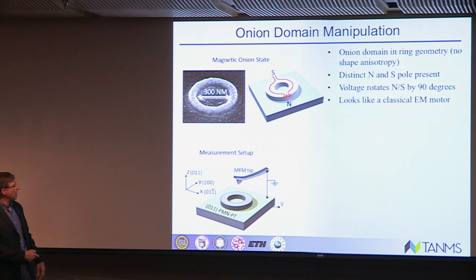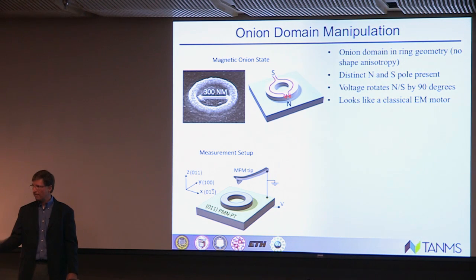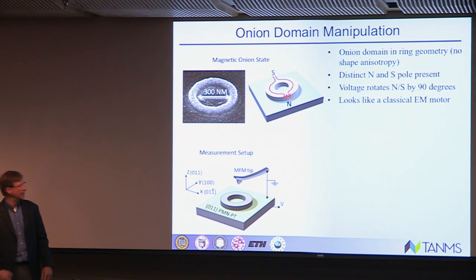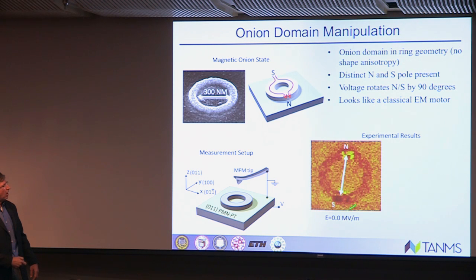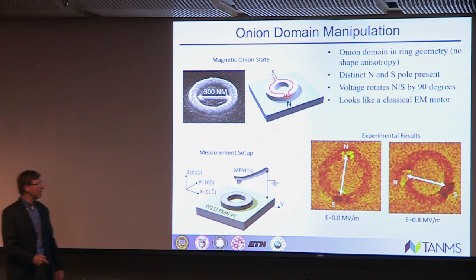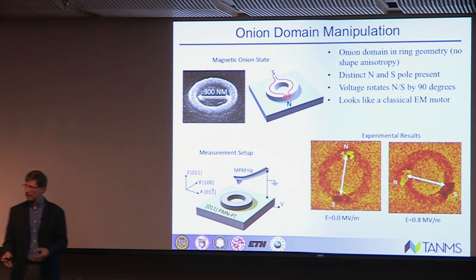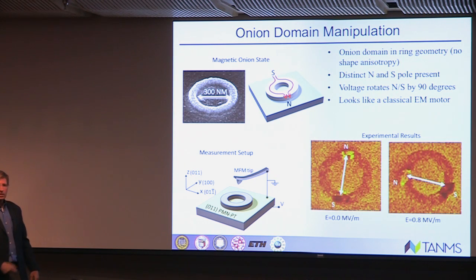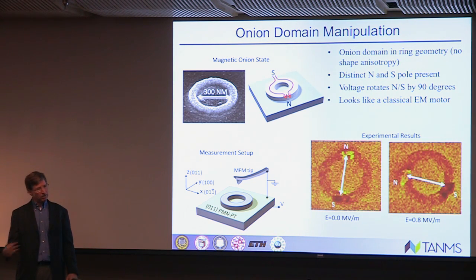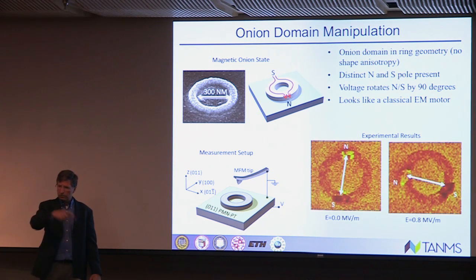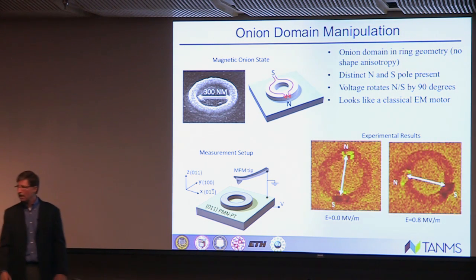So once again, we go in and we study this structure with MFM imaging, which once again is over here at CNSI. And what we do is we come up with our initial onion state. This is the north pole here. This is the south pole at 0 megavolts per meter. Now, all of a sudden, we apply an electric field, and lo and behold, we've rotated that by 90 degrees. And once again, I want to plant the seed. If you look at the structure, you go, wow, that just looks like a conventional electromagnetic motor. All you got to do is run that north and south pole around the ring, and now you have a motor. But now the motor's at 300 nanometers, not several centimeters.